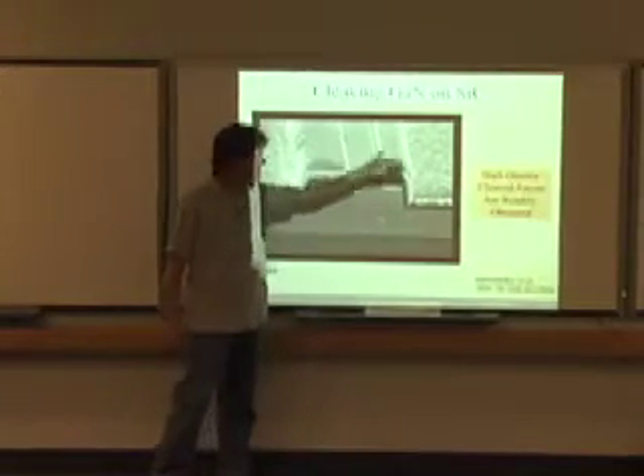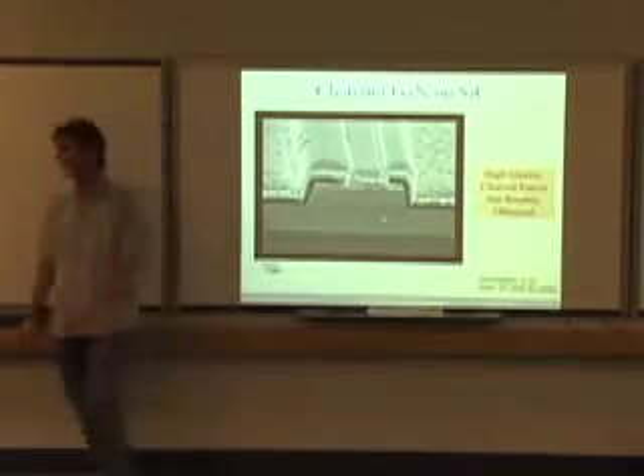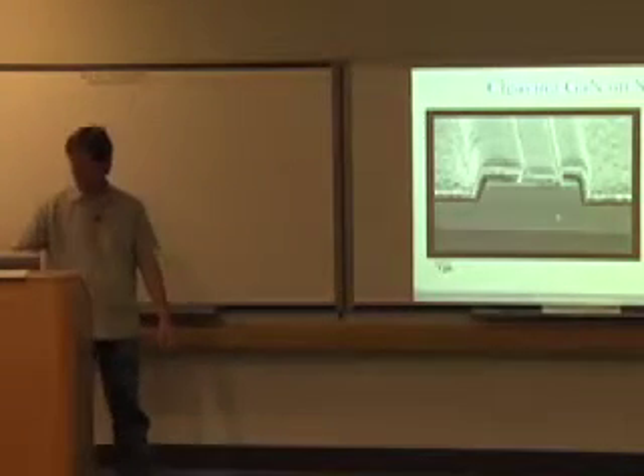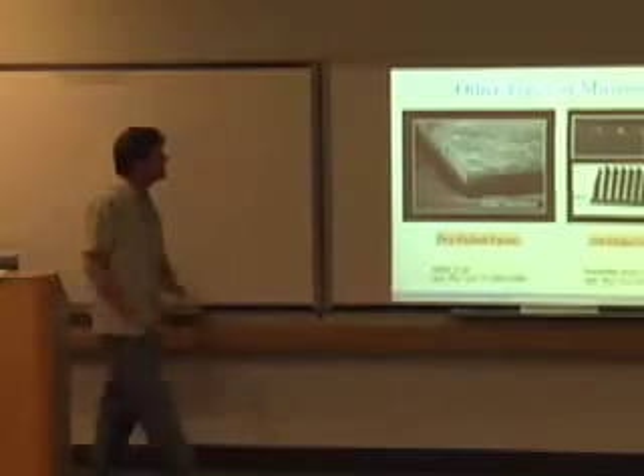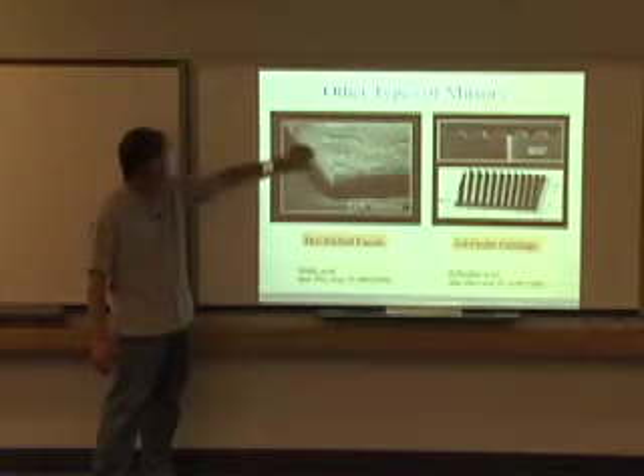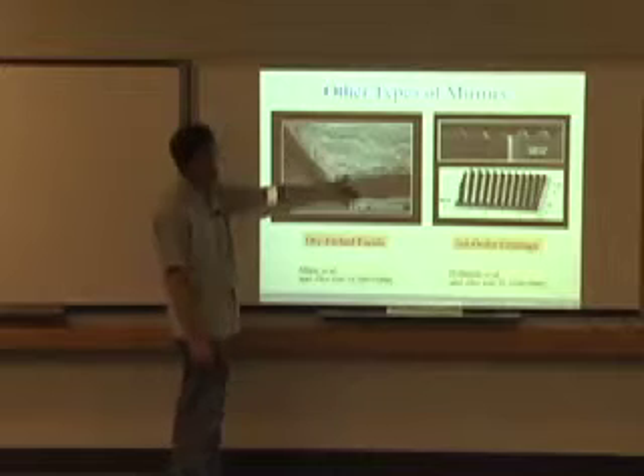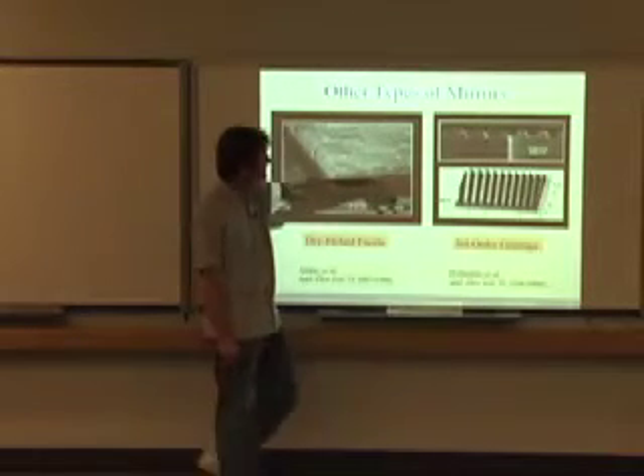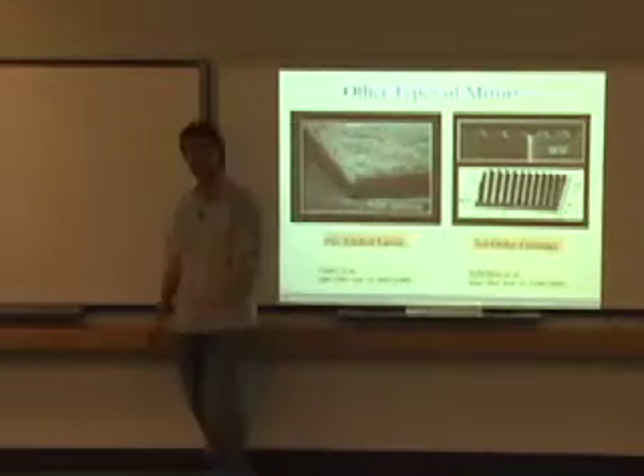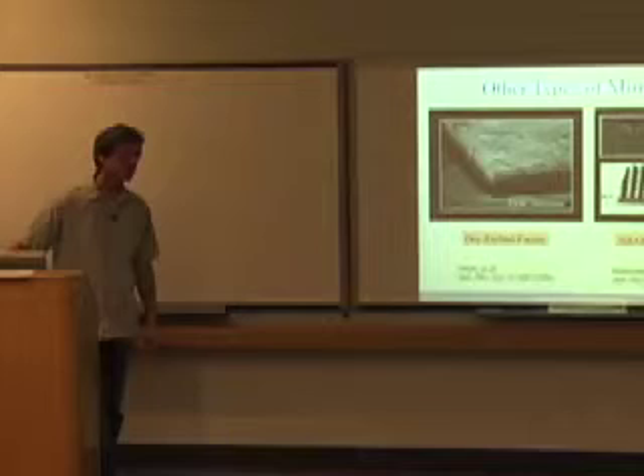Alternatively, if you're growing on silicon carbide, it's much easier. You can cleave the gallium nitride and get very nice, smooth quality cleaved facets. So people who are growing on silicon carbide generally cleave their facets. Another way to do this is through dry etching. Here is one of her pictures from Santa Barbara showing some nice dry etching of the sidewalls. And Nakamura also did that in the beginning with dry etched sidewalls, dry etched facets. Other people, with Zrock, have managed to actually make third-order gratings and make DFB lasers out of gallium nitride.